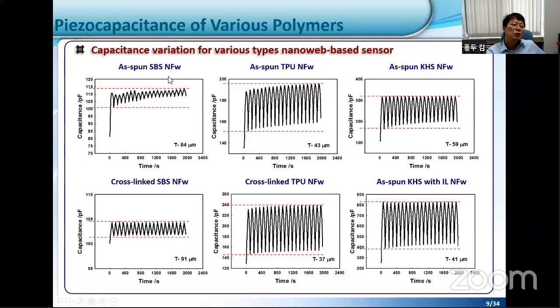But as you see here, using SBS as the material, the capacitance changes only about 5 picofarad. It's very tiny. Also, the behavior is not as good. Each peak means one cycle, where we apply force from 0 Newton to 100 Newton, and we accumulate 20 cycles. Then we cross-link the SBS, and the behavior is much better than the spun nanofiber, but still the capacitance change is only about 30 picofarad. It's not good for real applications.